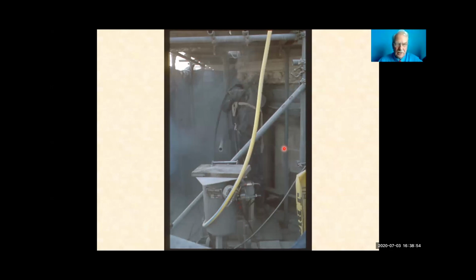We have tried laser cleaning. We found it to be very ineffective. It will remove some sorts of paint. It's very, very slow. Remember, I'm talking mostly about architectural and structural metalwork, so a process has to be quite fast. Otherwise, it becomes entirely uneconomic. We've found that it doesn't work very well on removing rust, except if it's fairly thin rust. And it's far too slow to be cost-effective on architectural and structural metalwork. It's much more for museum application, metalwork in archaeological and museum applications.